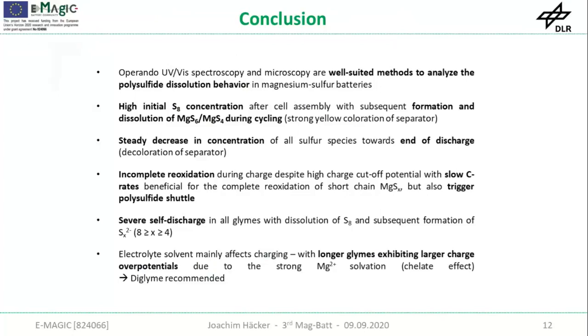During charge, an incomplete reoxidation is observed, even despite the high charge cut potential. Slow C rates are beneficial for this complete reoxidation, but only for the short chain polysulfide. So the long chain polysulfides are still present and are involved in this polysulfide shuttle.